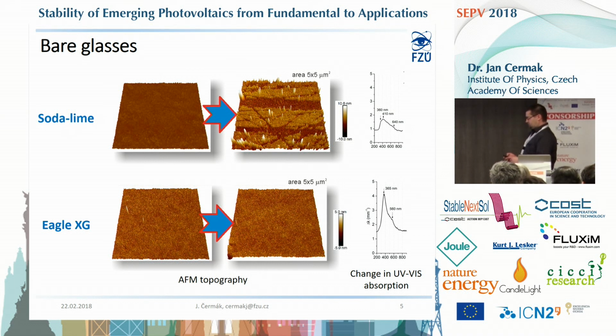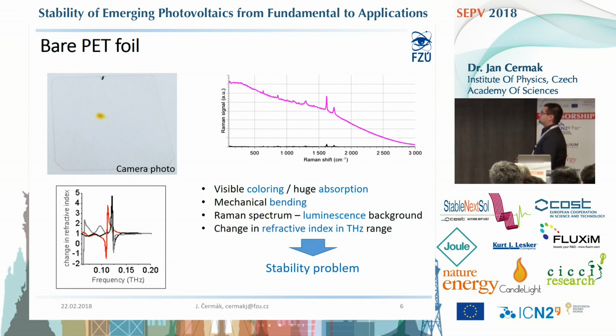It was a little bit worse with the polymer foil. Even with the naked eye, we can see that the irradiated area turns yellow to brown, which corresponds to a very huge increase in absorption. We could see some differences in terahertz spectroscopy. When trying to measure Raman spectroscopy, we faced the problem of a huge photoluminescence background. At first, we couldn't even see the Raman bands, so this line was captured after several optimizations. To say it modestly, the PET foil exhibits some stability problems when facing the protons. But the story as a whole is not that bad.